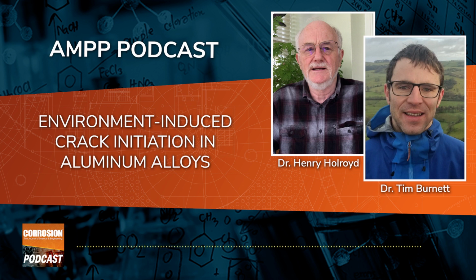I think we can talk more later about the challenges of that, but really it's been difficult to research historically, because that event of going from no crack to a crack can be almost instantaneous, and it's also happening at a very, very small scale. So we've got something very fast and very small, but that event of cracking initiation, nucleation, can take place after days, weeks, months, years.